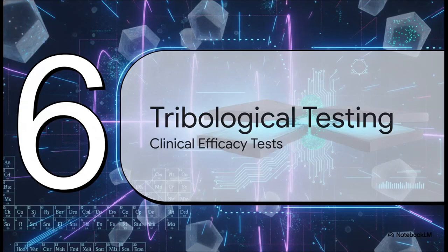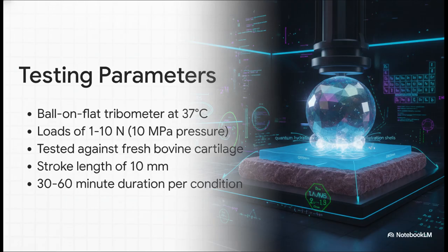Finally, Section 6, Tribological Testing and Clinical Efficacy. The final hurdle for the optimized QSM hydrogel is surviving extreme physical stress in tribological testing to prove its clinical impact. We use a ball-on-flat tribometer set to 37 degrees Celsius against fresh bovine cartilage. We subject the hydrogel to loads equating to up to 10 megapascals of pressure. That is an immense, bone-crushing amount of force where traditional supplements instantly fail.